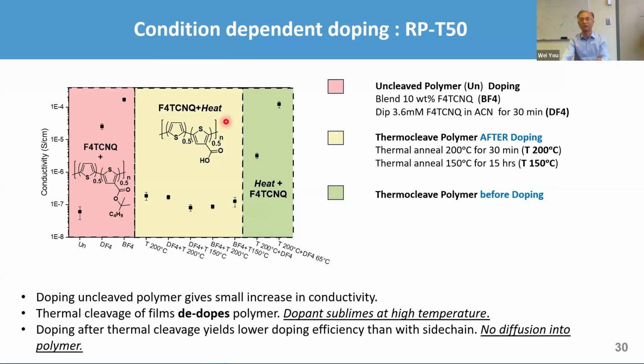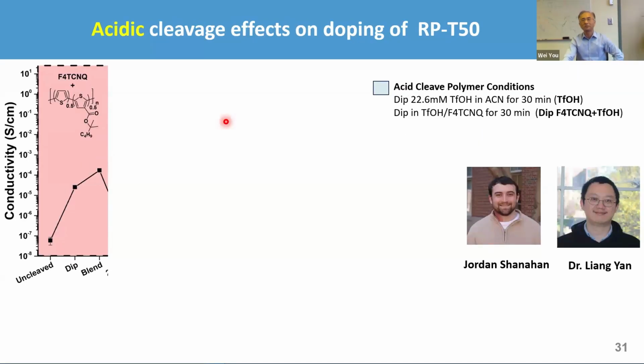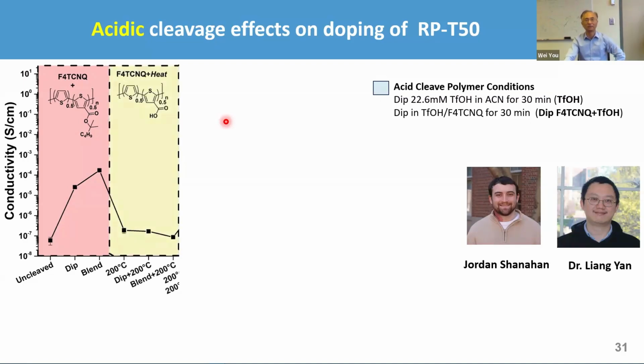So this is precisely what I meant earlier, that the thermal approach has a very strong limitation because of the high temperature. So the next thing we did was actually using the acid. That's where the magic is going to happen. All right. So same thing on the left panel. You do the heat, the same thing happens.